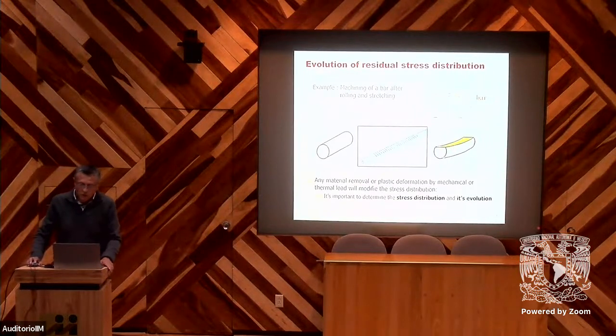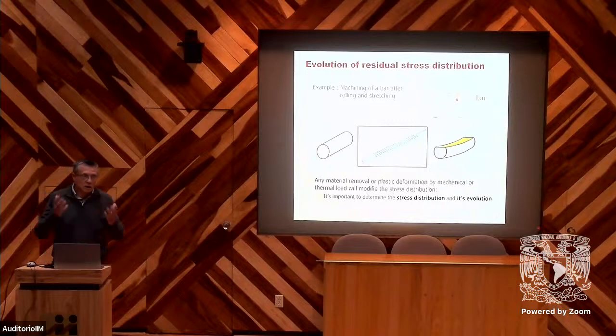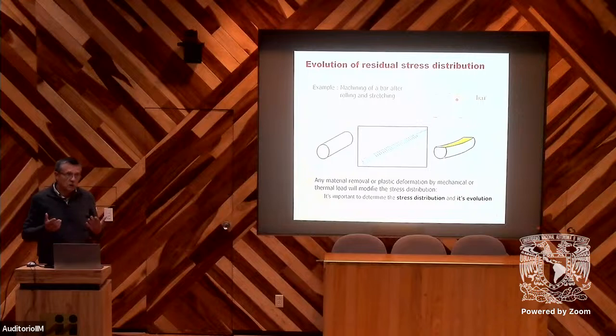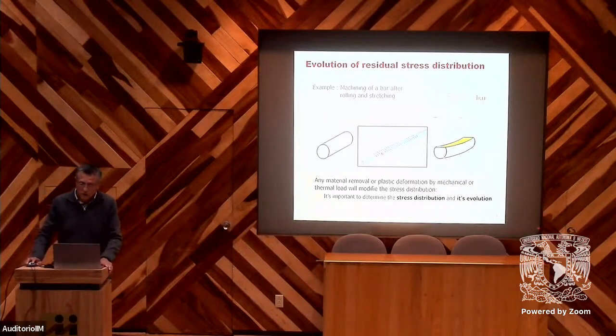Another effect, no less important, of residual stresses is distortion. After rolling or forging, we can get residual stresses inside the materials. These residual stresses are equilibrated. So if we remove material after these operations, we need another equilibrium, and this will induce distortion. For example, in this piece for an automotive application, we can get some distortion after machining.